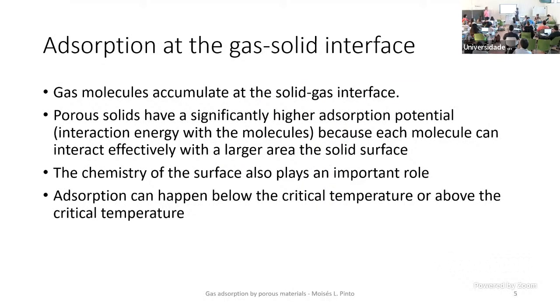So the molecules, like I said, accumulate at the solid gas interface. So porous solids have a significantly higher adsorption potential, so we have interaction energy with the molecules that go to the surface. This is what we call the adsorption potential, because each molecule can interact effectively with a large area of the solid. Yes, sometimes when you have pores, the pores we are talking about are on the same range as the molecular size. So if you have a molecule that goes inside this pore, the molecule feels the potential of several walls. Yes? Of course, if the pore is very large, what I'm talking about doesn't make sense anymore. So it's like a flat surface.